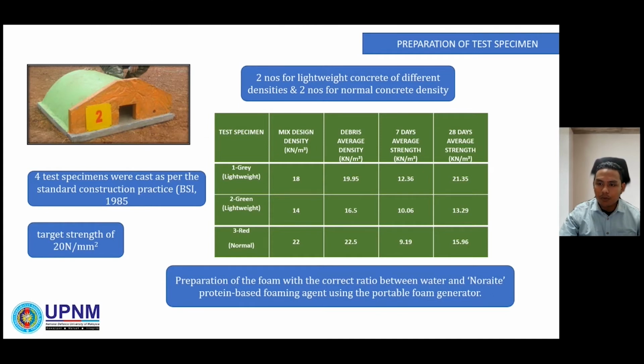Preparation of the foam with the correct ratio between water and Noraite protein-based foaming agent using a portable foam generator. A different color cement was used for the different densities of the concrete so that the blast debris collected can be differentiated from the different test specimens.